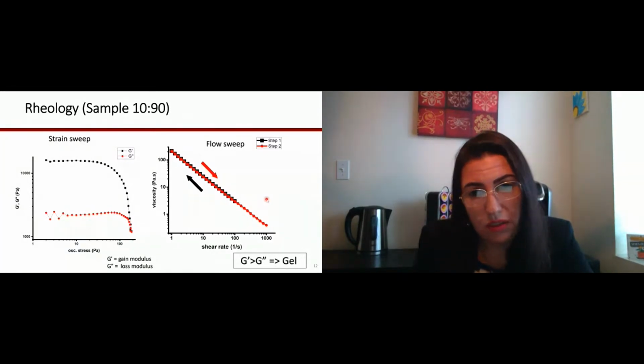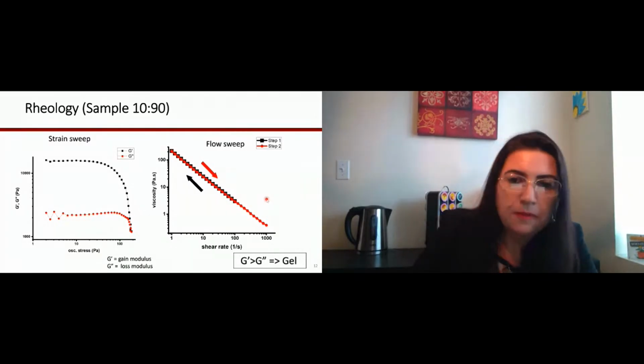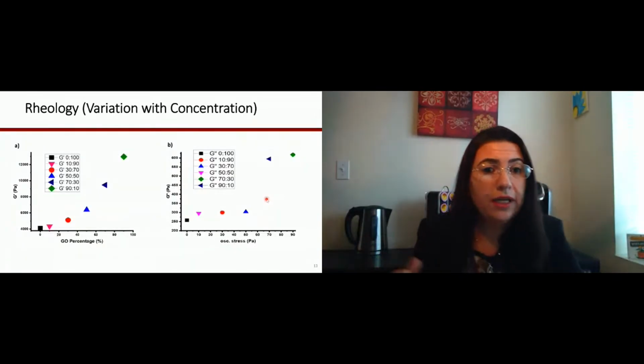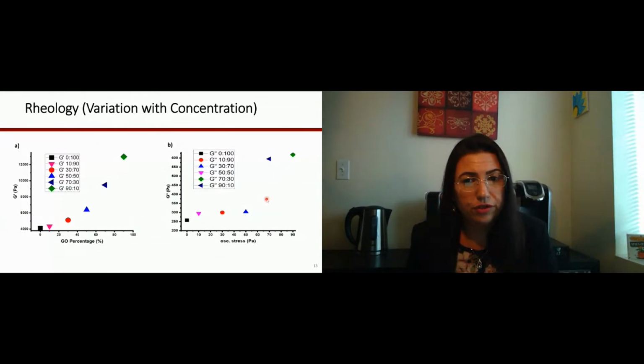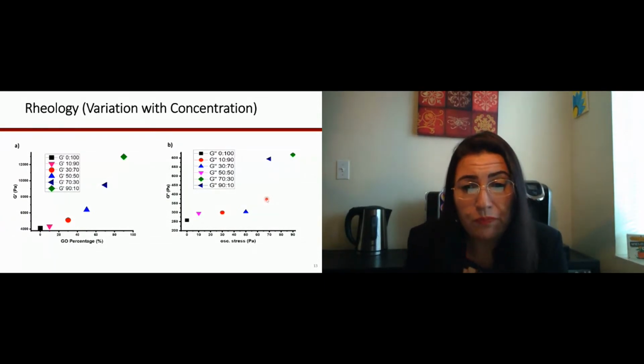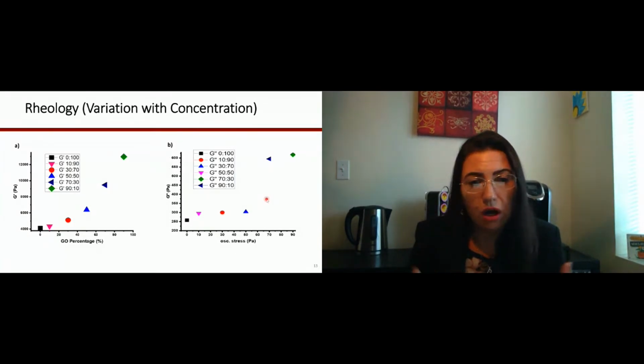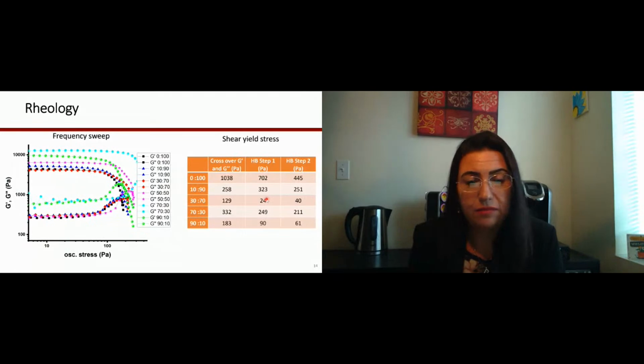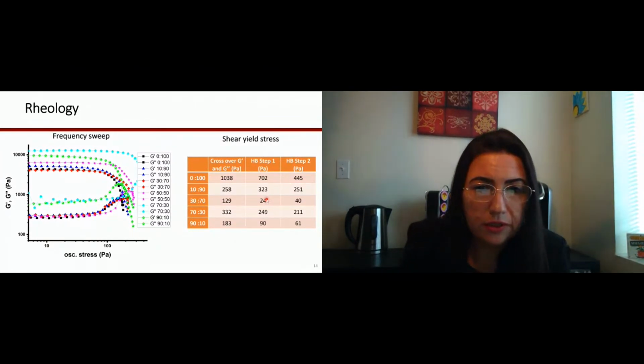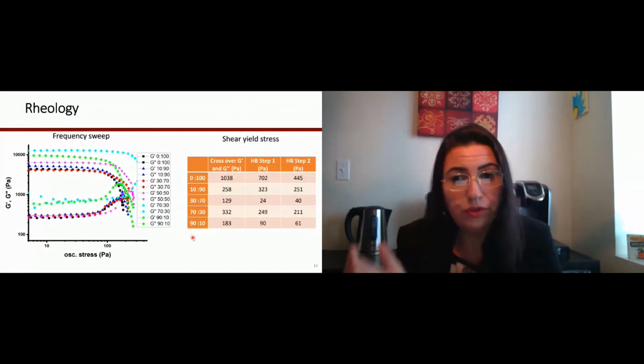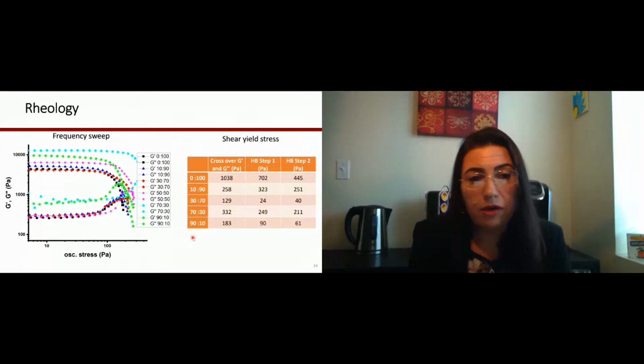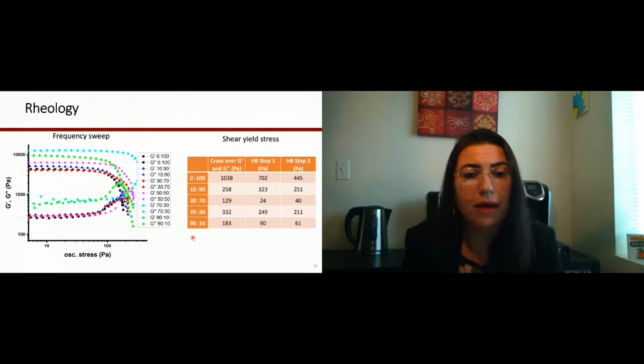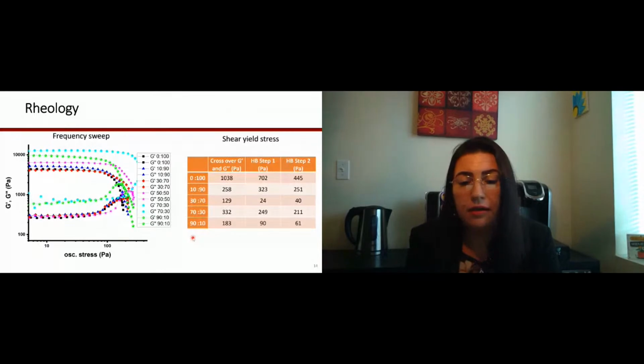It's cool to see that viscoelasticity. After that, we had the rheology done for all the different concentrations of graphene and MoS2. And the reason I think about the rheology is that there were two different ways to figure out the alignment of the printing. We could look at the crossover point between G prime and G double prime, or the Herschel-Bulkley model. So doing those two methods, we had to ensure that the pressure we were printing at was above the